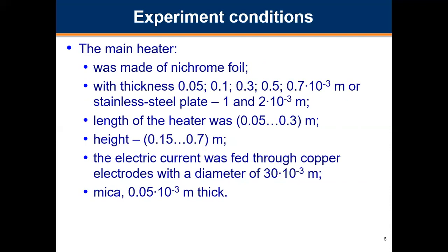The main heater was made of nichrome foil with a thickness from 0.05 to 0.7 times 10 to the power of negative 3 meters, or a stainless steel plate that is 1 and 2 times 10 to the negative 3 meters. The length of the heater was 0.05 to 0.3 meters. The height was from 0.15 to 0.7 meters. The electric current was fed through copper electrodes with a diameter of 30 times 10 to the negative 3 meters.